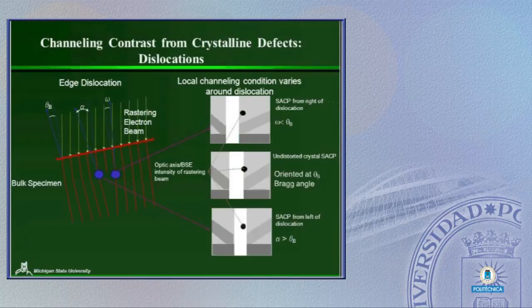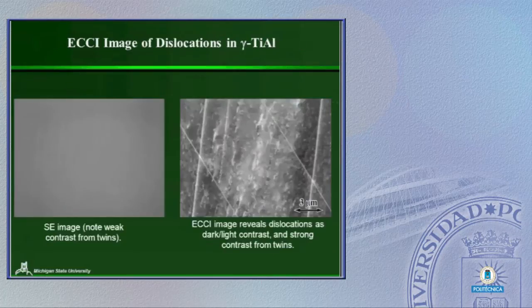If we want to see a dislocation, imagine this as a dislocation here. As we raster the beam across the sample, we can imagine that locally the orientation is going to change. And as a result, if we could imagine the channeling pattern near that dislocation, we can't measure that obviously, but we can imagine that the center of those channeling patterns will represent the local backscattered yield. And that local backscattered yield will be given to us by the intensity on that pattern at that given orientation. And because the pattern shifts as we move across the sample, we're going to get changes in intensity as the beam moves across that dislocation line.